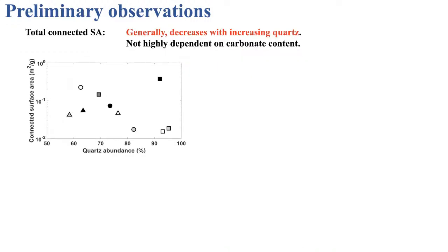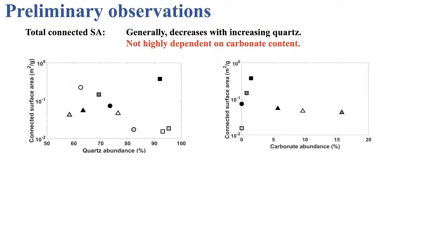If we look at the total connected surface area, we can see it generally decreases with the amount of quartz, which is kind of what we expected because quartz potentially has a smoother surface compared to other minerals. We see that it's not really highly dependent on carbonate content, so you have some initial increase when you have 0 to some small amount of carbonate, but then it's relatively stable.